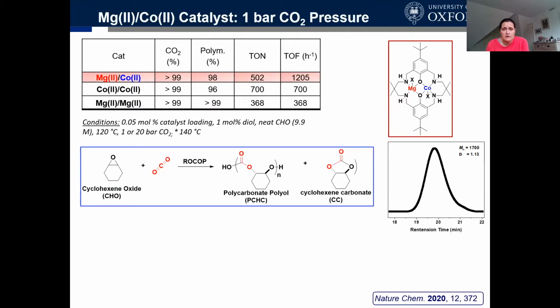There were other proofs that we used. I'm not going to go through them. They were to do with magnetism. But the important question is whether this mixed metal species is more active in catalysis. The short answer is that it definitely is. If you look at the turnover frequency data for polymerizations run at 1 bar pressure of carbon dioxide, you can see that it's showing about 1,000 to 1,200 turnovers an hour, whereas the cobalt is 700 and the magnesium is about 370. Those data are all conducted under the same conditions, so we can be sure that this is a proper comparison of activity. And we're really seeing a much higher activity for the mixed metal species than we might expect.